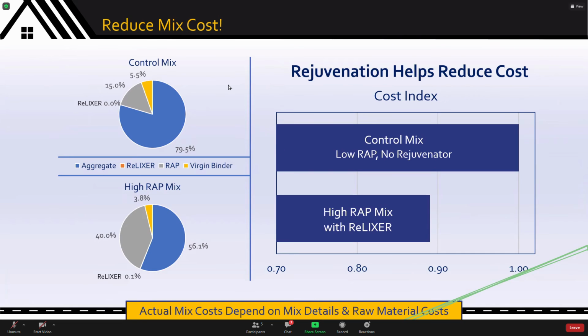Here are two mixes, a control mix made with 15% RAP and no rejuvenation. This is the cost index of that mix. This is another mix made with 40% RAP and about 0.1% by weight of rejuvenator. As you can see, the cost of the high RAP mix with ReLIXER is anywhere from 5 to 15% lower, based on your local circumstances.